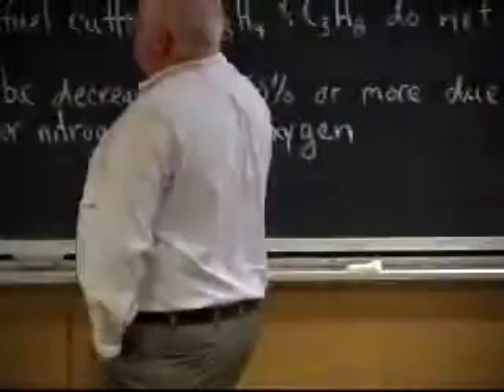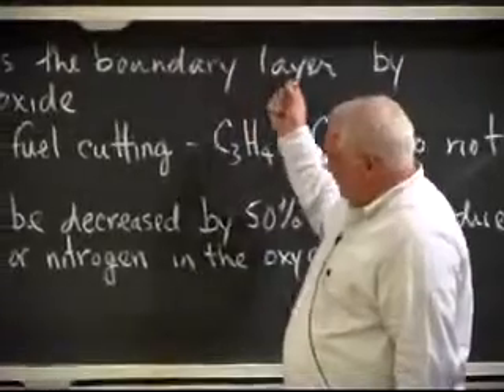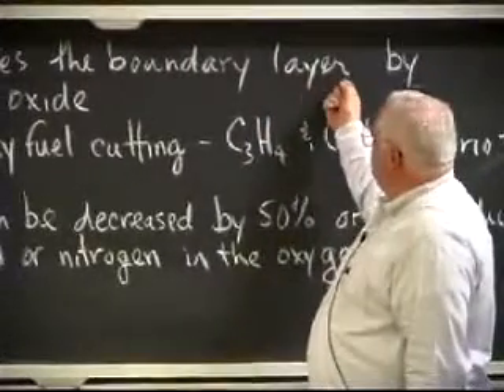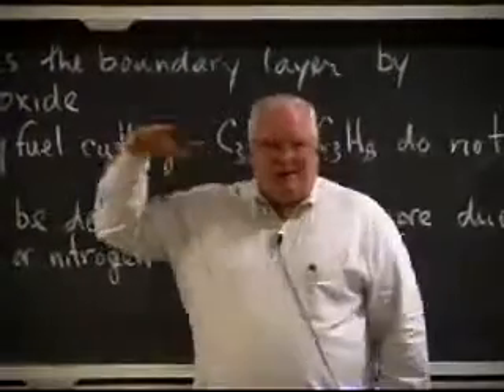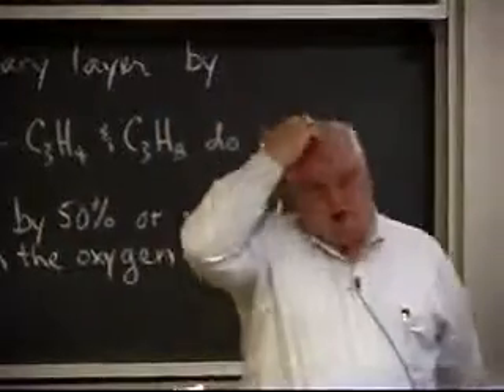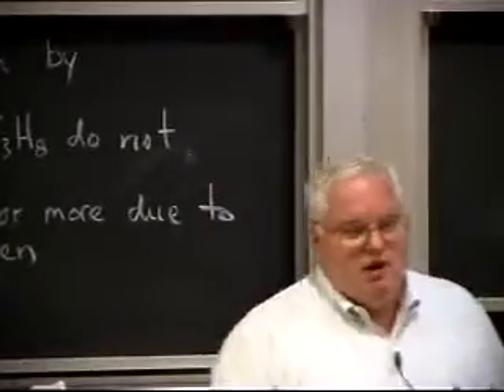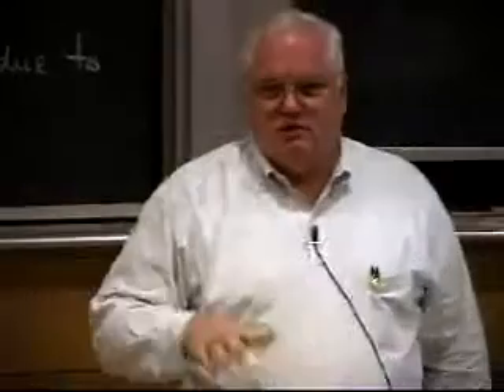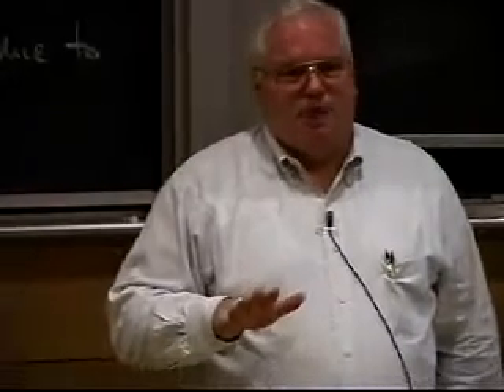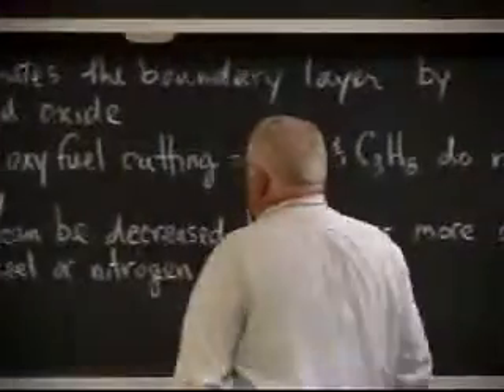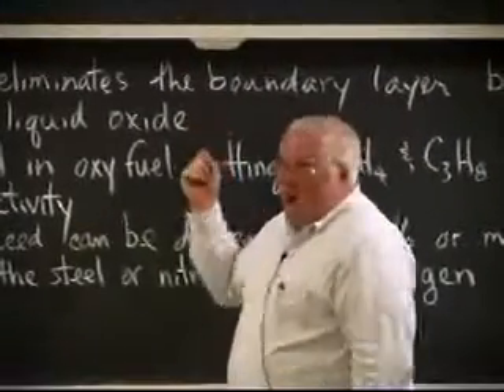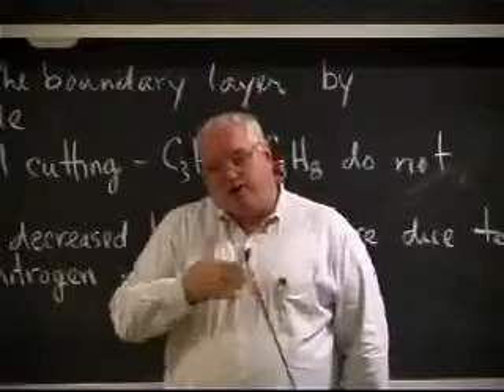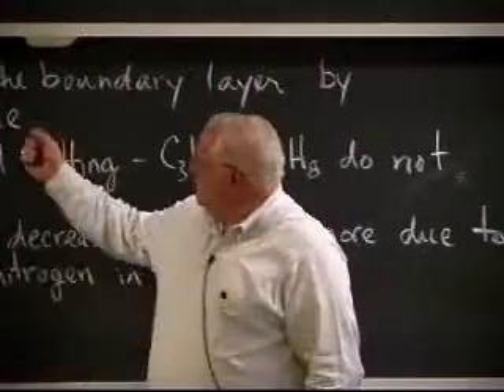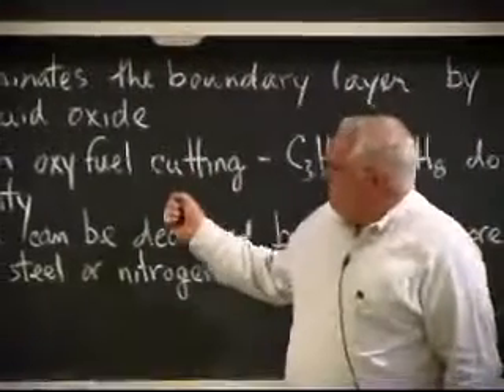We talked last time about oxy-fuel cutting, and we mentioned that basically you get very high heat transfer rates in oxy-fuel cutting. You're essentially eliminating the boundary layer by condensing it to form a liquid oxide. Iron oxide forms, and so the gas that's coming in this flame turns to a condensed phase, and so there is no boundary layer. And so you don't limit the heat transfer to the surface because of the boundary layer. And if you go through all that, you find that you get about a 50-fold increase in heat intensity because there is no boundary layer.